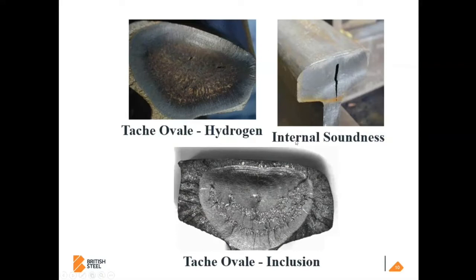Here you can see poor internal soundness from a pipe defect in a pre-1976 rail, which has caused the rail to split. And another Tache Ovale here from a non-metallic inclusion within the steel prior to mandatory ultrasonic inspection. So again, a stress raiser internal, and it's cracked from the inside out. And you can see that field side flow on this image as well, with the sharp corner and the round corner. It's surprisingly common, that.